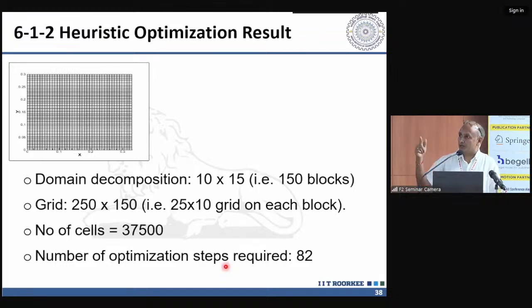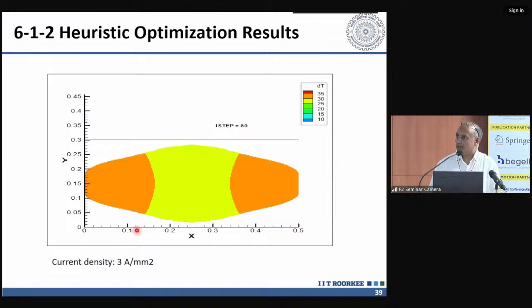For the heuristic approach, we have taken a simple structured grid of cell-centered finite volumes, with 37,500 cells. And this is the result after 82 steps. Though significant reduction is taking place compared to the earlier initial geometry of 500 by 500 square, we're still not satisfied with the temperature.